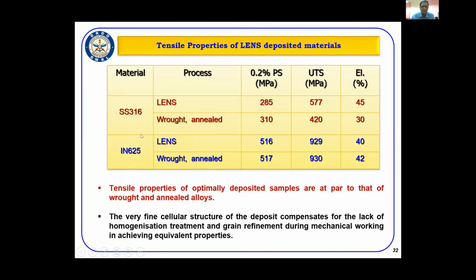We have also evaluated the tensile properties of the deposited materials for 2 different materials, 316 and 625, as shown here. They are all near to the wrought and annealed properties. These are the properties we obtained with the optimal process parameters. Using these parameters, the deposited samples are all at par with the wrought and annealed material. We have seen a very fine cellular structure in the deposit, which compensates for the lack of heat treatment. That means as deposited itself, we were able to get properties near to the heat treated properties. This has been attributed to the very fine cellular structure we have got, which compensates for the lack of homogenization treatment and grain refinement during mechanical working, achieving equivalent properties.